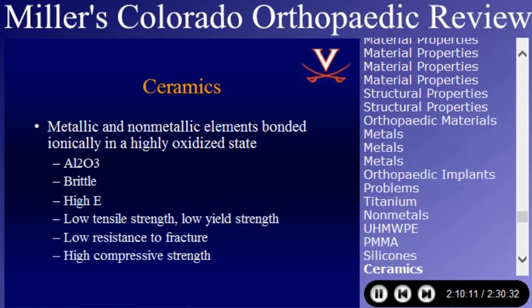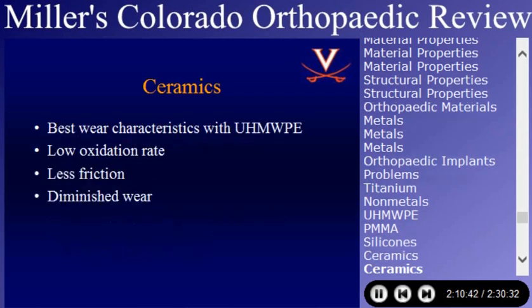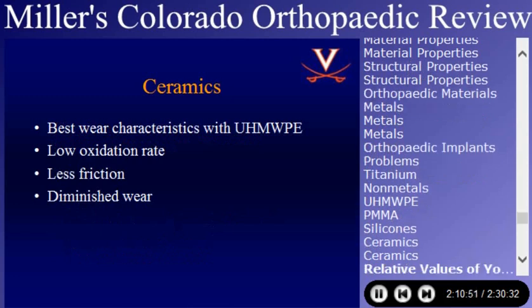Ceramics, again, touched on in the total joint lecture. It's metallic and non-metallic elements bonded ionically. So it's an ionic bond. That's been on the test as well on the previous question. It's an ionic bond in a highly oxidized state. Alumina is an example. It's very brittle, but it has the highest elastic modulus. So it's very stiff, but when it breaks, it breaks. There's no area of plastic deformation before it breaks. Low resistance to fracture, but it's very good in compression. So ceramics have better characteristics than polys. They have a low oxidation rate, less friction. They produce less particles, and they have diminished wear.